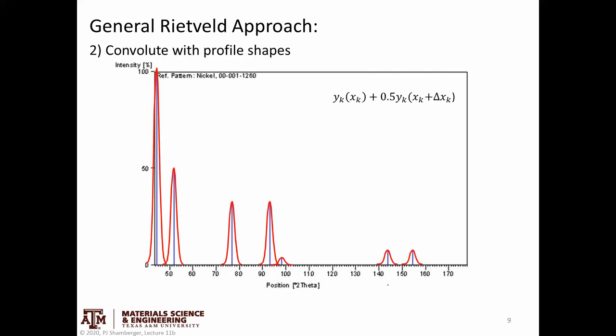On a real diffraction system, the peak is not a perfect delta function — there's some finite width to it. We get this width by convoluting that intensity — that infinitely narrow spike — with the profile shape. Each peak has some profile shape, and the peak shape may have angularly dependent terms, getting a little broader at higher angles. We apply that shape equally to all the different peaks.